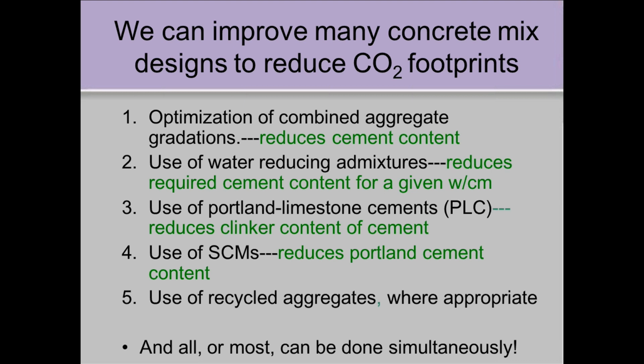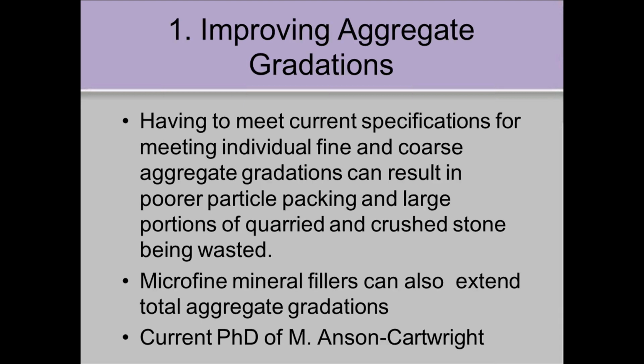And recycled aggregates, I think, is one where we have to use them where appropriate, but we can use them. So the problem with the aggregates, and I think a number of agencies in the U.S., various state highway agencies, and others have recognized this in the past, we're just a little slow on the uptake, is that meeting the individual coarse and fine aggregate gradations leaves a gap in the middle. You end up with a gap-graded mix. And it's a huge impact in urban areas because they're blasting these quarries, sieving it out for coarse aggregate and throwing a whole bunch of undersized material away that's not allowed in the specification because of the gradation envelopes. And then they end up with the sand and they end up with a gap where the stuff they've just thrown out would fit.